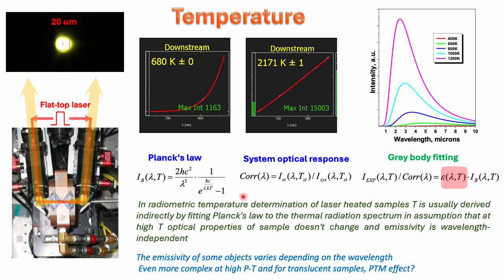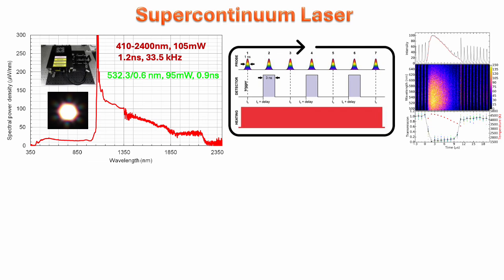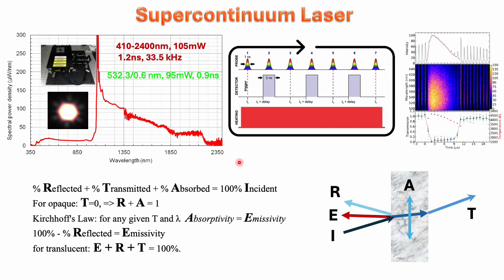To avoid that, we have decided to do a new development. We use a supercontinuum laser to measure absorption and reflectivity of the samples. You can see the supercontinuum laser has very nice intensity in the visible and infrared range, and if we combine it with the laser heating, we can measure absorption and reflectivity of the sample during laser heating. Applying simple considerations, if we have enough absorption and reflectivity, we can get the emissivity of the sample and use it for the temperature fitting.